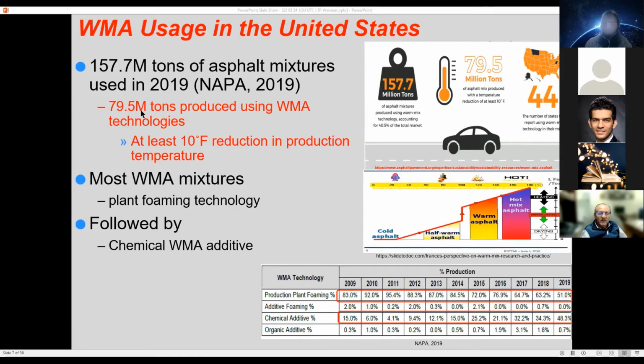So we are making headway in including those additives into asphalt mixtures from the time when it was introduced about 10, 15 years ago. And also that particular study showed that typically 10 degrees F is used to reduce temperature, and most WMA mixtures use plant foaming because you don't have to add anything. And the second thing that is used is to include some additives.